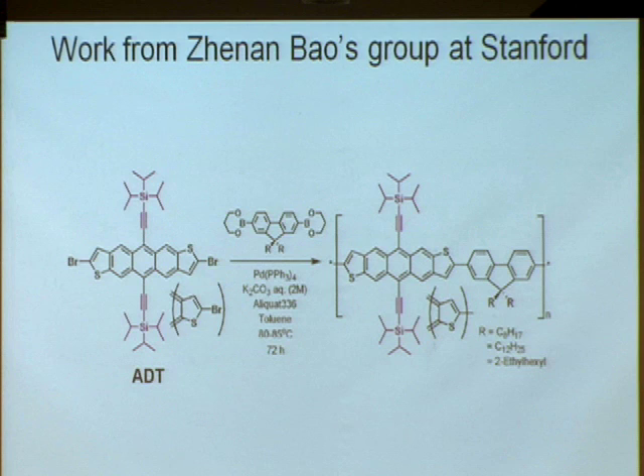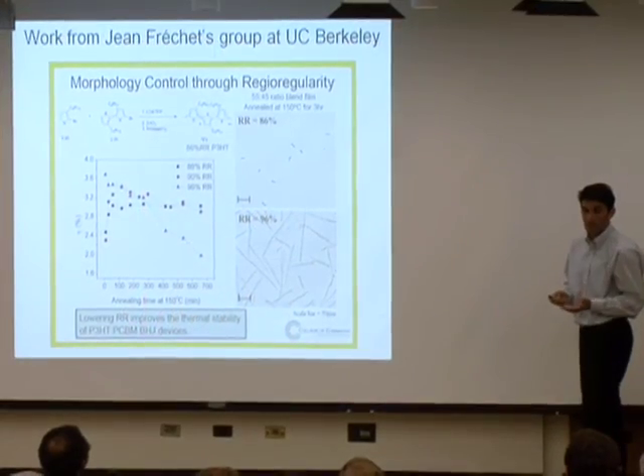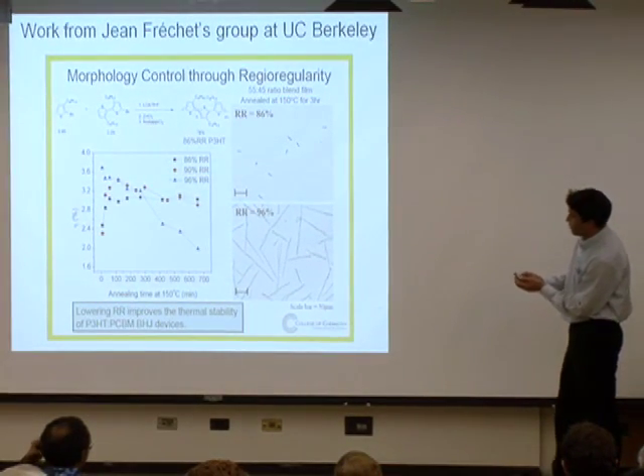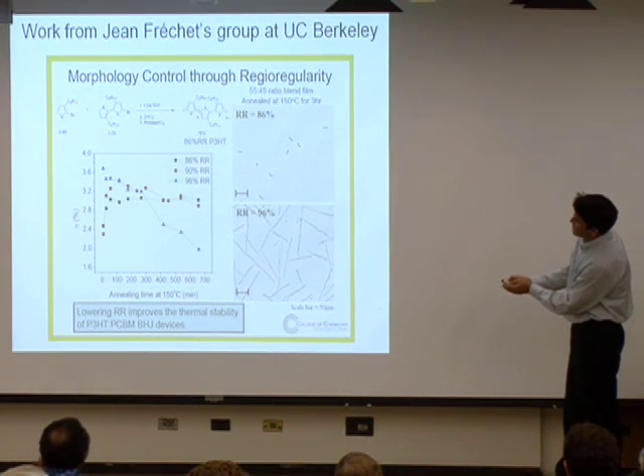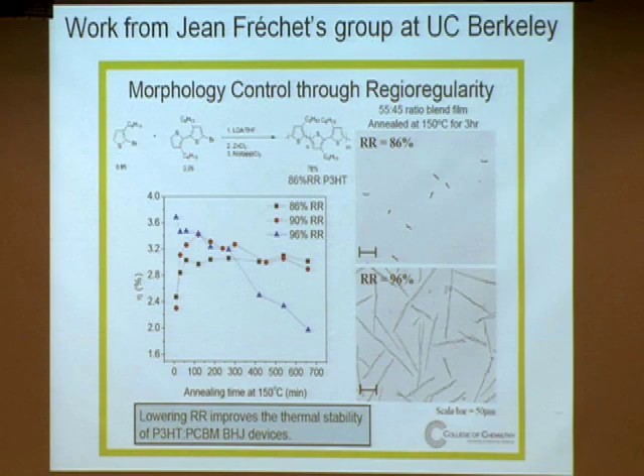And the last example here is basically going into morphology. So I've been talking about energy levels, but now you can look at morphology. So it turns out if you make certain materials, you have a different level of crystallinity in the solid state version. So you have one material that you can polymerize and you can make these things very crystalline. So this RR is just referring to crystallinity. You can plug in certain materials in that polymer backbone and you can systematically reduce this crystallinity.